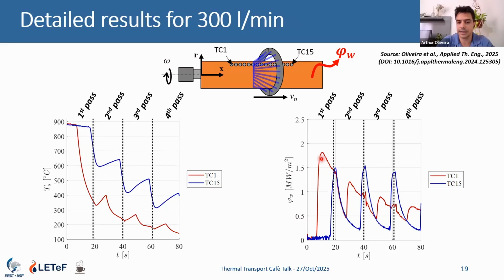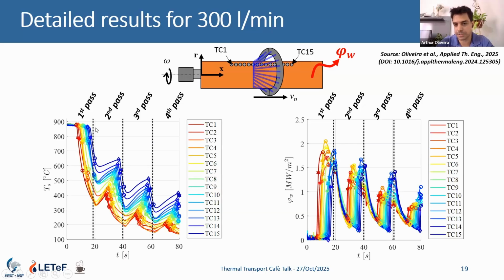Here you can see the evolution in the heat flux over time for each thermocouple. I put here only 2 thermocouples to make it easier to see, because here we have the key points that I showed you before: the onset of cooling before the temperature drop, the maximum heat flux point here in the middle of the temperature drop, and the maximum cooling rate point somewhere in between. I can do that for all 15 thermocouples.